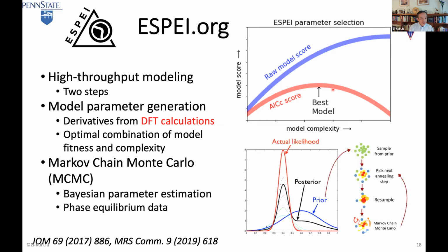extrapolability. And then it's very important to realize that DFT data has a large error bar. If you use this data to calculate phase transformations or phase boundaries, it could be hundreds of degrees off, so it's not useful; it's far away from experiment. So another kind of data is the phase boundary data, from the MPDS. Then you can refine the model parameters, based on a parameter estimation method. It's a Markov chain Monte Carlo to refine the parameters. This refining process at the same time can generate uncertainty for the parameters when you have input data uncertainty.